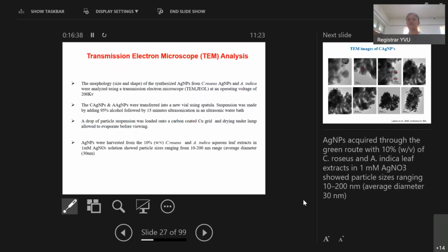After that, the morphology, size, and shape of the synthesized silver nanoparticles were analyzed using transmission electron microscope. The operating voltage is 200 kiloelectron volts. The AgNPs were transferred into a new vial using a spatula. This suspension was made by adding 95% alcohol, followed by 15 minutes ultrasonication in an ultrasonic water bath. A drop of particle suspension was loaded onto a carbon-coated copper grid and dried under a lamp, allowed to evaporate before viewing.